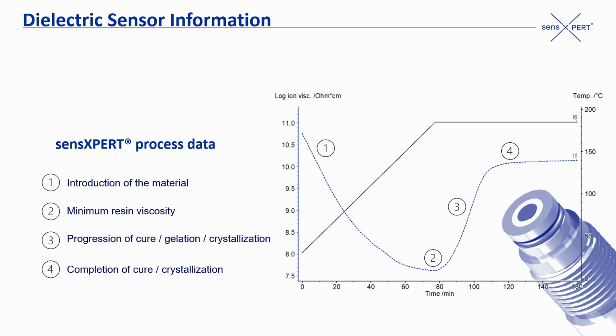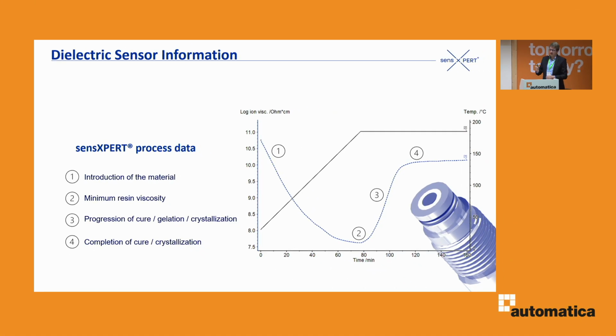When we apply some temperature to the material in the process, the plastic will see an increase in temperature. First thing that happens is the viscosity decreases. The plastic becomes more fluid. And this is what we see when the dashed line is dropping. At some point, we reach a minimum, and then this line goes up again.